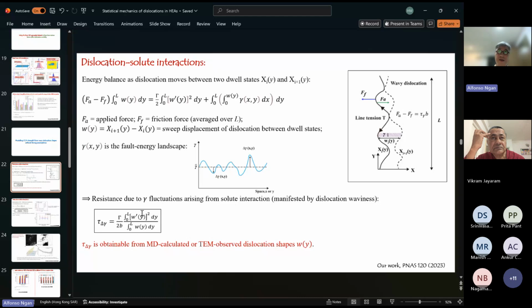Here a lot of physics is hidden in these two integrals. Instead of using a very intensive model starting from first principles, I'm hiding a lot of physics into these two integrals, basically the shapes of the dislocation. And instead of using intensive models, I use MD data or TEM data to obtain the dislocation shape to help me calculate the resistance term.